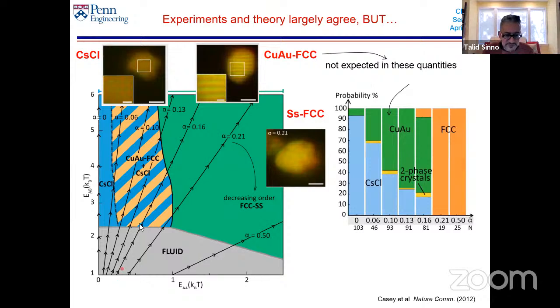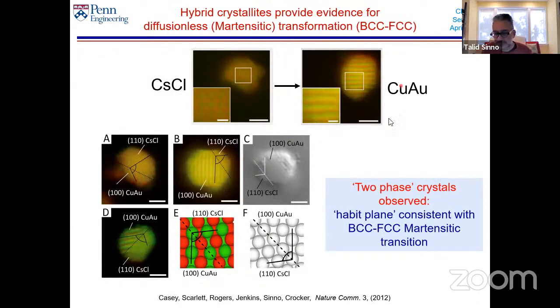So when you follow one of these lines, as you're in here, you form a cesium chloride crystal. And then by the time you push it into this part, it will spontaneously just change shape and form a copper gold crystal. And the evidence for this was pretty profound. If you look at some of these crystallites, you can actually see crystallites that have half and half character. So you can see that this was a crystal that started as cesium chloride, and then it transformed into copper gold. And this was caught in the middle of that. This transformation was arrested in this case. And we see many of these.